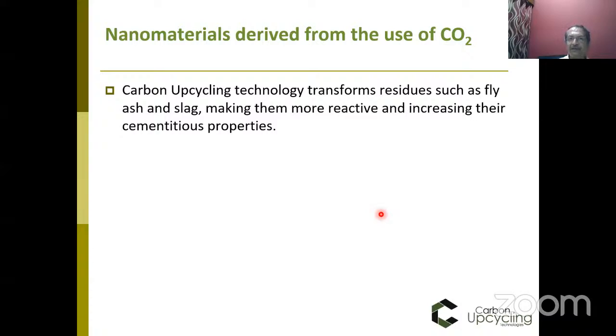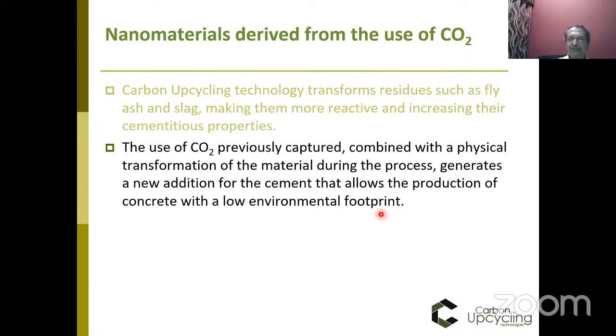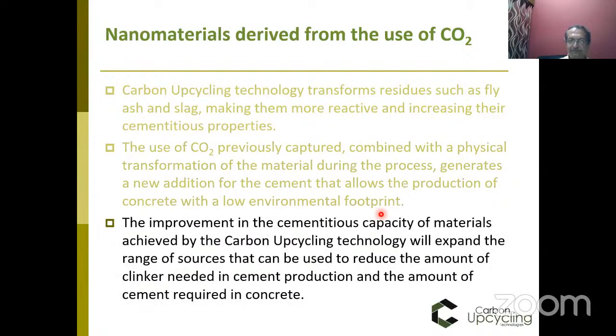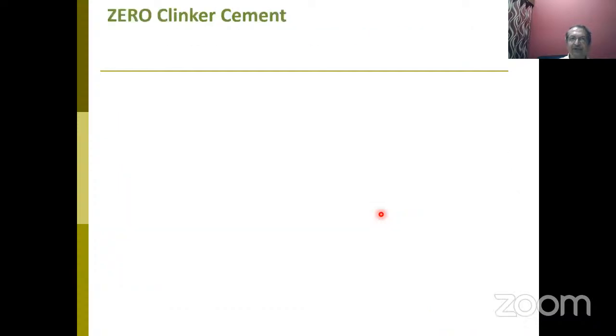Carbon upcycling technology transforms residues such as fly ash and slag, making them more reactive and increasing their cementitious properties, which means we can incorporate more of these materials into cement, thus reducing the OPC content within the cement itself. So the use of carbon dioxide previously captured, combined with physical transformation, can create a new addition to the cement that allows for production of concrete. The improvement obviously is evident for everybody.